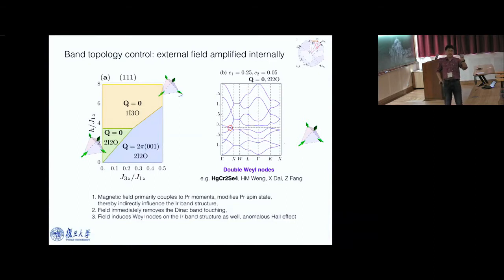Because the energy scale between the local moments is pretty low, you can easily modify the magnetic state by coupling to the external magnetic field. This is an example of applying the field along one direction. Then you can change the state from 2-in-2-out finite Q into 2-in-2-out 0Q, and then into 1-in-3-out 0Q. You can change the magnetic state, and this has actually been observed by Nakatsuji.